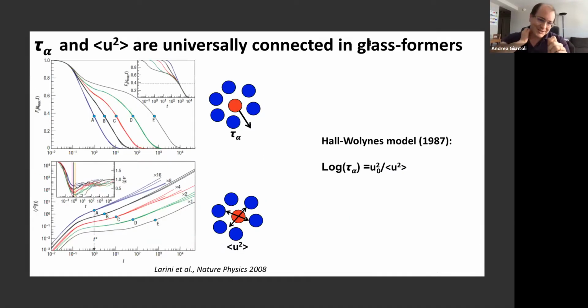So here is where it becomes cool. The idea that I'll show you now is that if you take two different systems with different conditions, different temperatures, different chemistry, different molecular structure, interactions, whatever, if they have the same alpha relaxation time, they also have the same Debye-Waller factor.